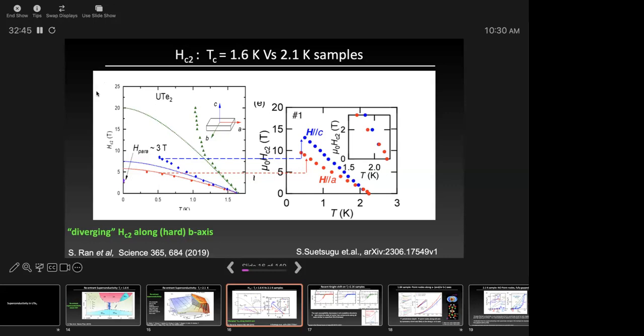Just to be clear, you're talking about the transition at the beginning of the superconducting state. You're not talking about the fluid state, right? Here? Yes. This is the regular one, down there. Correct. Exactly. These temperatures are well within this fluid transition or the fluid peaks in specific heat. So it's a controversial subject. For these samples, there is no split transition. But if I were to take a 2.1 sample, one peak and one fluid melt, what is the second peak? Here in the 1.6 Kelvin samples, it's very close to 1.6, just less than a Kelvin. It's not two different phases. Some of the 1.6 Kelvin samples showed two peaks, but they were very close to 1.6 Kelvin. They were not close to 2.1.